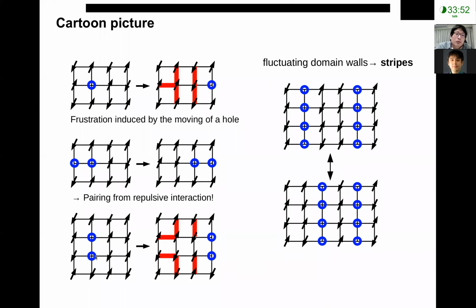However, if we move the holes in another way, it still has this high energy spin. So a clever way to do it is to align the holes in one direction to form this stripe, with different domains in between the stripes. And now the holes, or this stripe, can freely move left and right without messing up the antiferromagnetic patterns.